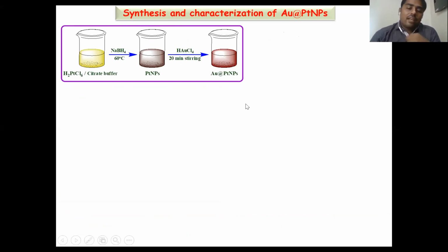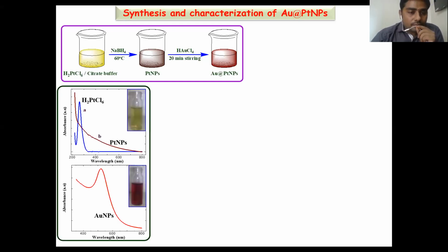Keeping in mind the above literature studies, we prepared gold platinum bimetallic nanoparticles in solution form and then fabricated them on the electrode surface for the methanol oxidation reaction and O2 reduction reaction. Initially we prepared the platinum nanoparticles from platinic acid with the help of a strong reducing agent, sodium borohydride, and then we added auric acid to the solution to form gold platinum nanoparticles.